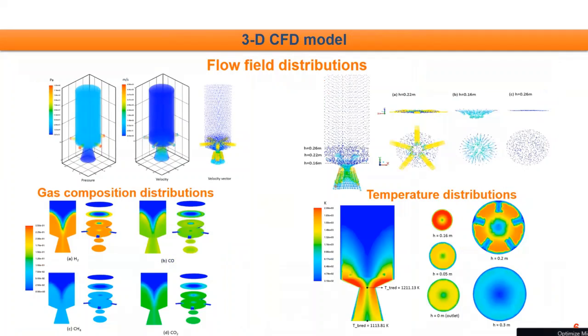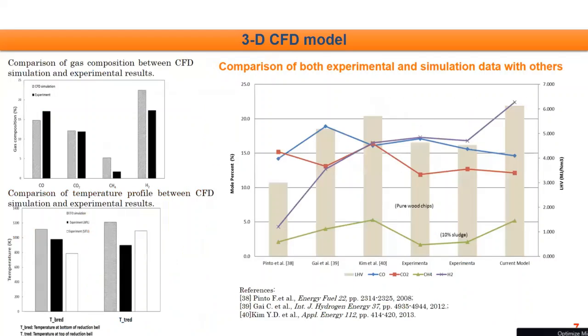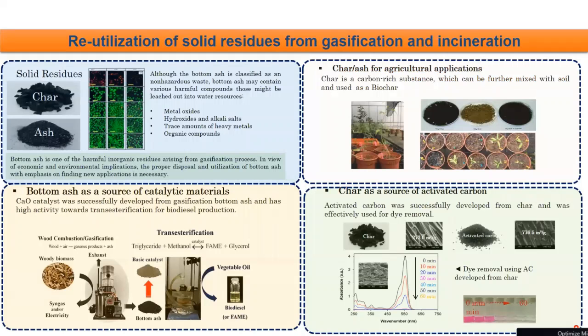This shows you some snapshots of the resultant flow field, temperature, and the producer gas composition in the gasifier. This slide shows you the comparison of simulation with experiment. We were able to benchmark the simulation result with experiments. Hence, that closes the loop starting from the feedstock to produce syngas and potentially biochar.